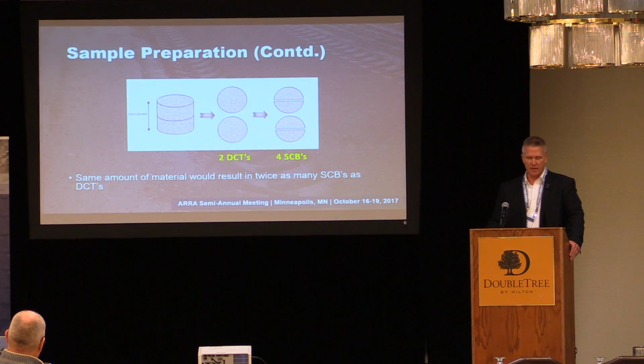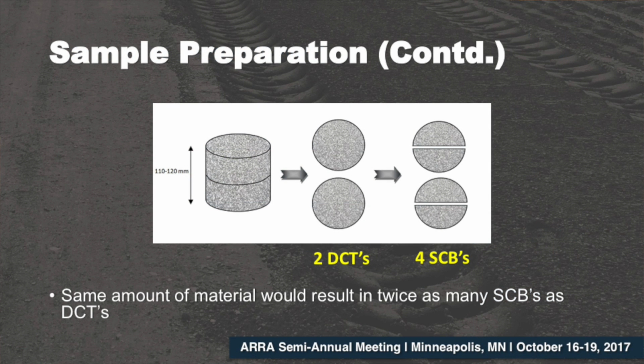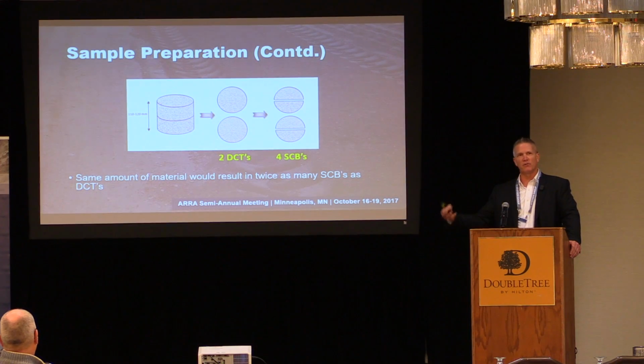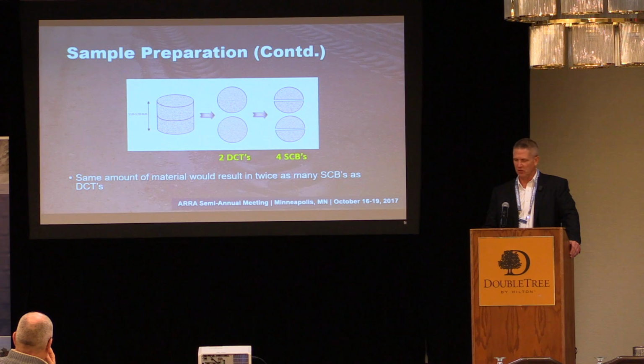So you can see here that in terms of the sample preparation, you either have a gyratory specimen, or if you're talking about a field specimen, you're taking a core from the field. From that specimen, you can come up with 2 DCT specimens or 4 SCB specimens. So as you advance to doing quality control, quality assurance in the field, the ability to get more samples from the specimens is certainly an advantage when you're looking at correlating the material that's being placed back to the mix design or back to what you're trying to achieve.